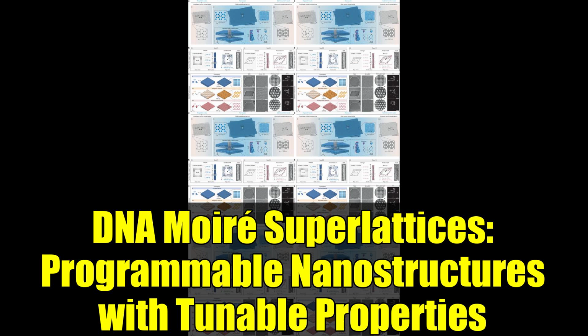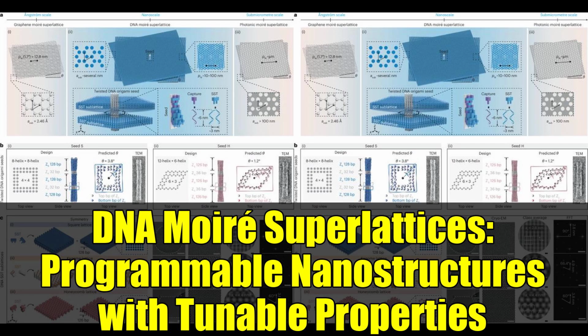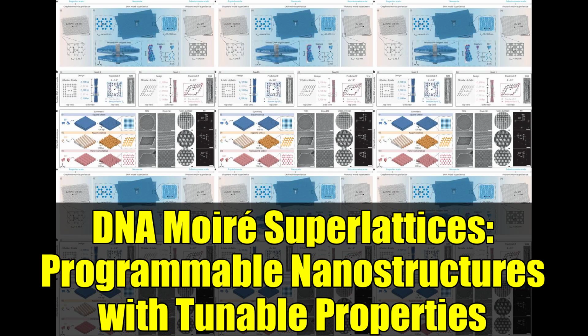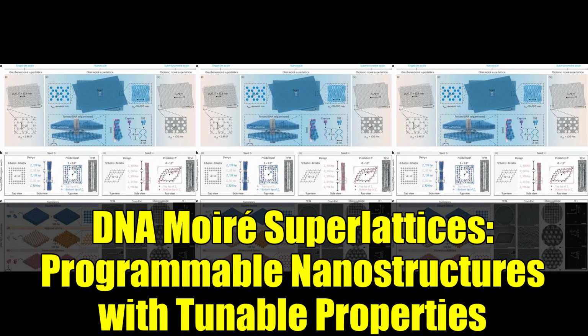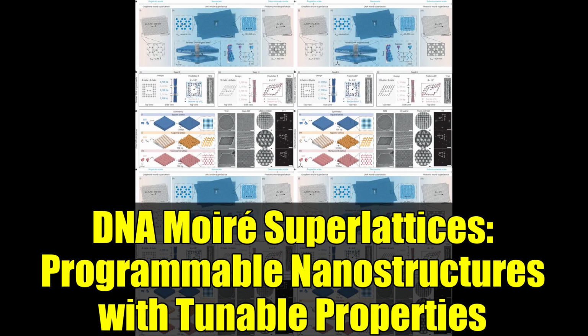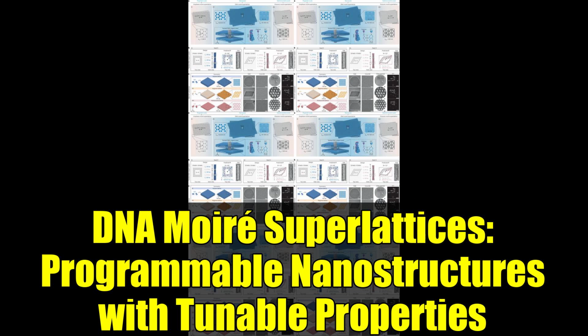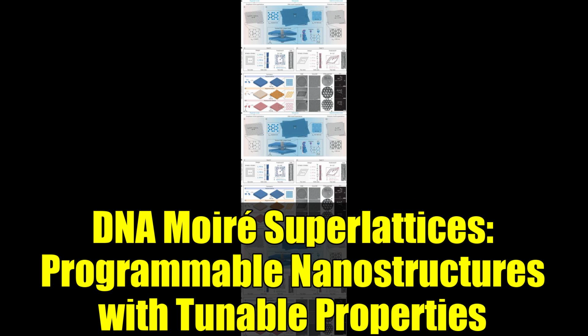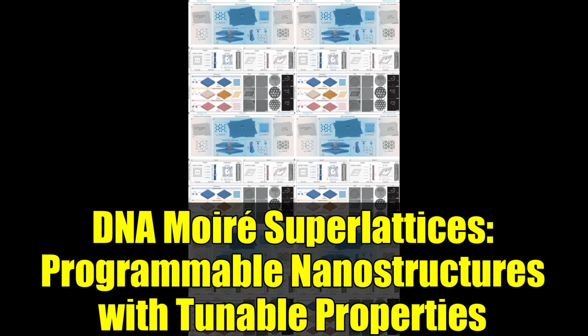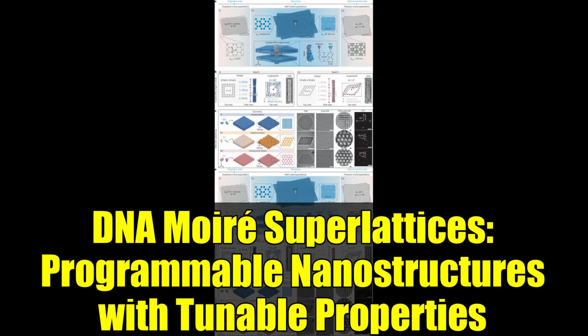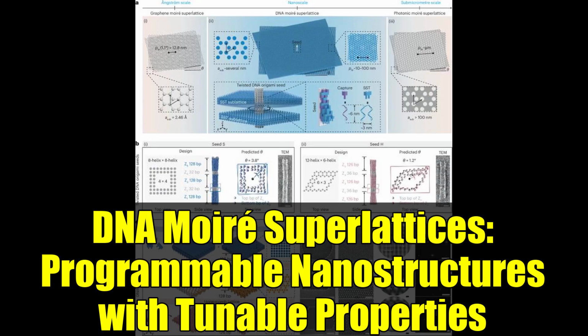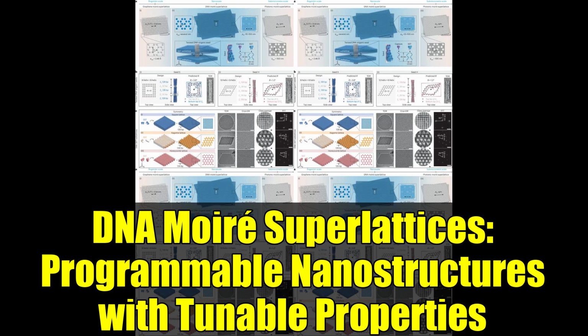This is where DNA nanotechnology boldly enters the scene. Using ingenious bottom-up design, researchers constructed entirely new classes of Moiré superlattices from DNA, bridging that daunting nanometer gap. How? By engineering programmable DNA origami seeds, tiny, twisted DNA bundles that act as templates, and using controlled self-assembly of single-stranded DNA tiles, SSTs. These nanoseeds aren't simply passive scaffolds. Their internal twist and modular binding sites actively dictate the stacking, rotation, and registration of 2D DNA sublattices around them.